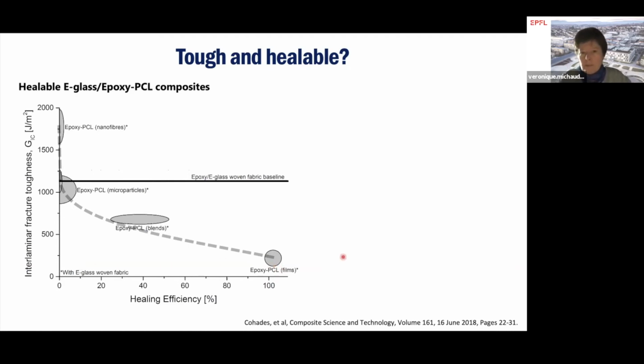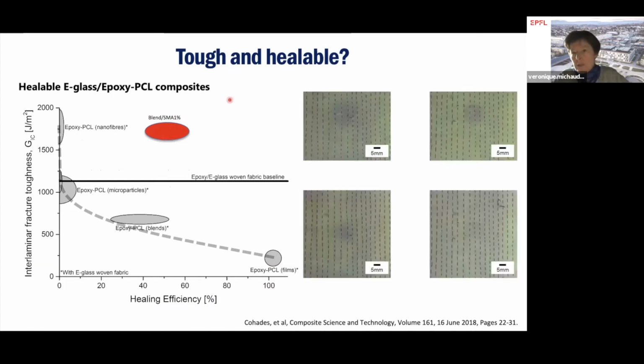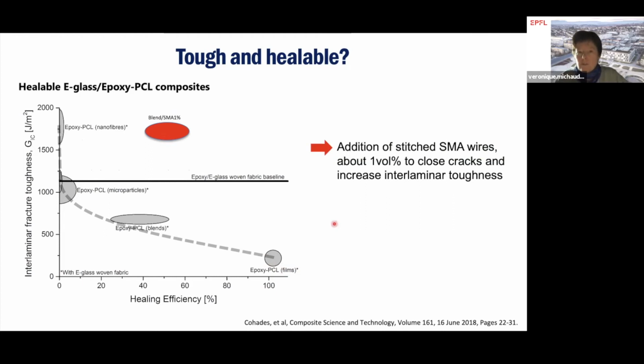So to get to a place where we get decent healing and decent toughness, we tried different things. One was to blend, use the same blend or similar blends, but with shape memory alloy wires, and only with 1% of these shape memory alloy wires that are stitched inside on the fabric and then impregnated as usual, we got decent results.